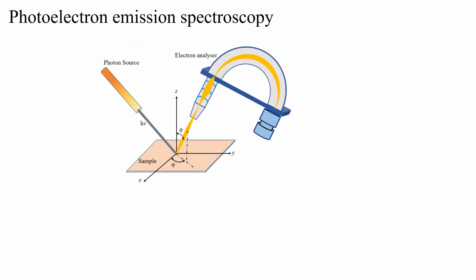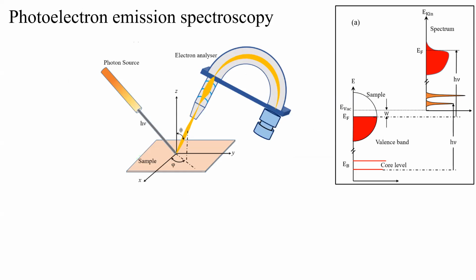Now, what is the photoelectron emission technique? It's very simple and complex. Simple in the sense it's based on the photoelectric effect. So basically you shine a light on the sample, electrons will absorb those photons, and they will come out from the sample. Of course, it will come out only if the incident photon energy is sufficiently high. So if I draw the right side of this, it is the sample's electronic structure. You have very sharp features which are basically the core levels, and then you have a very sharp cutoff at the Fermi energy also.